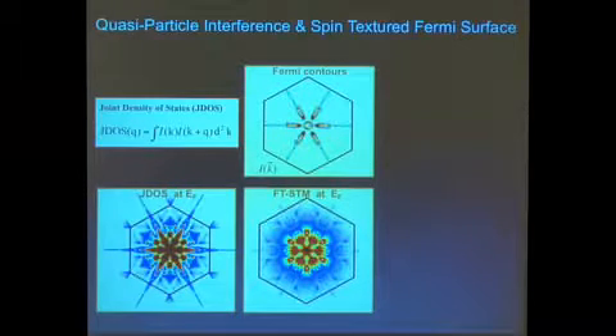So the holes are in the center, yes. So if you're an electron or a hole living on this Fermi surface, basically you can explore it by scattering from the alloying defect that I have put in the sample. So you might think that if I have all these possible ways of scattering electrons in this sample, if I equally explore it as a function of the momentum transfer Q, I can just convolve this data with itself and compare that with what the STM data is telling me.